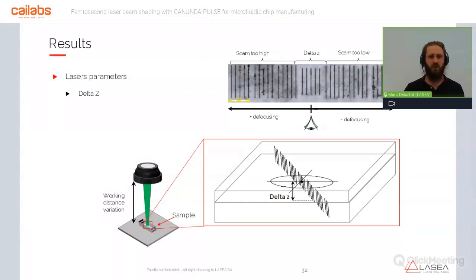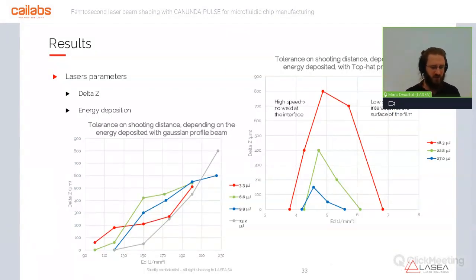And now I will speak about our results. To determine our laser parameters, we use a value that we call the delta Z. We make different lines at different vertical positions by moving the scanner, and we observe for each value whether the welding seam is correct, or perhaps too high or too low. The interval of vertical position values where we have a correct welding, we call the delta Z. We made this job for different values of energy deposition.